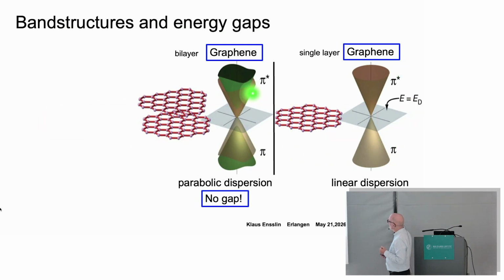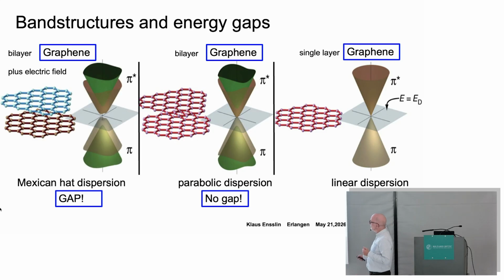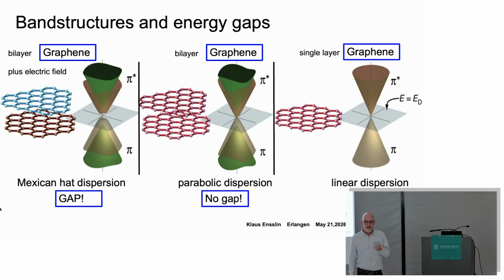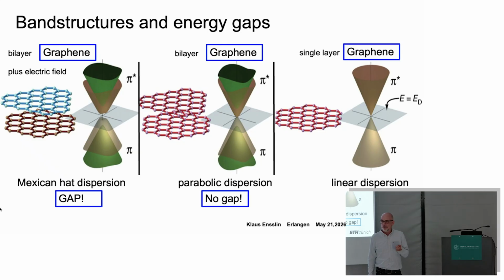So you go to bilayer graphene. Bilayer graphene is just 2 layers of graphene on top of each other. It looks similar in dispersion. It's not quite the same because close to zero energy, you have a parabolic dispersion. It's not linear anymore, it's parabolic. And you have various bands because you have the two layers. And you can break the symmetry by applying a vertical electric field across these two layers. And then you see you open a band gap between these two layers. And a band gap is something that you fundamentally need if you want to confine carriers in a solid-state system.